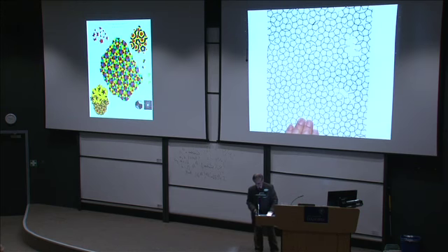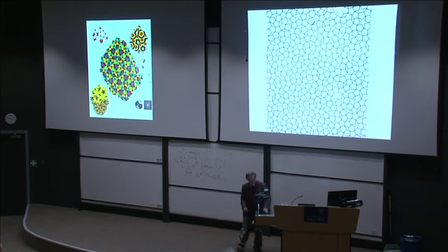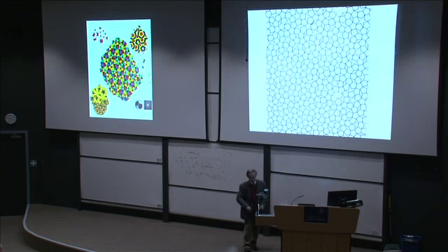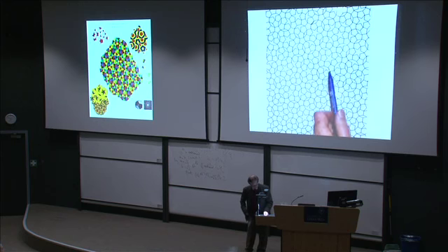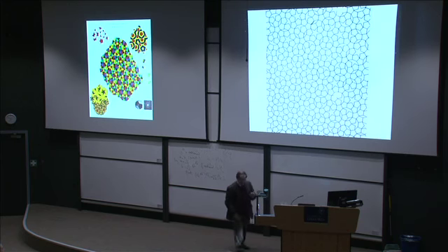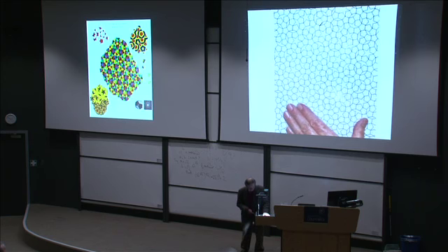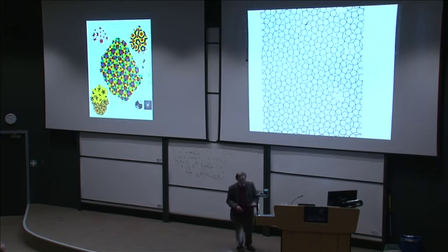Now, what about this pattern? It looks as though it's both symmetrical in the sense that you can translate it and it goes into itself, and has fivefold rotational symmetries, with a lot of stars, pentagons, and things like that. In fact, both those statements are almost true. This pattern could be extended to infinity, and I'll show you how you can do that. Extended to infinity, it has the property that if you give me any percentage less than 100%, say 99.9%, then I would be able to find a way of sliding that pattern along itself, a translational symmetry, so that it goes into itself to 99.9%.